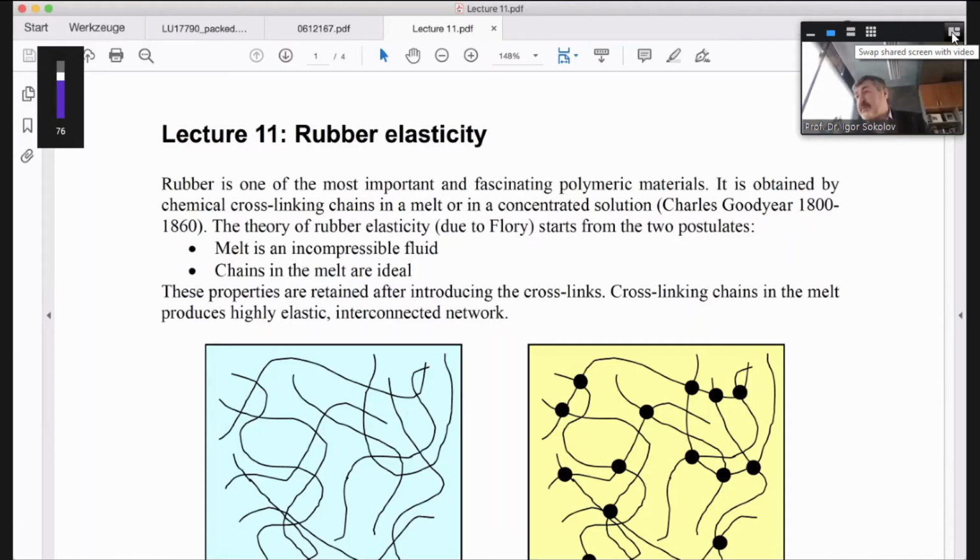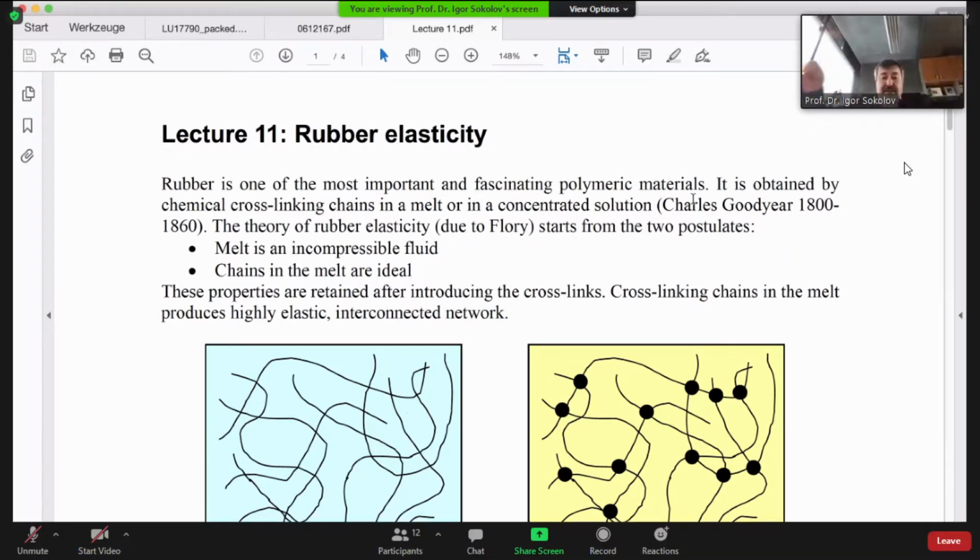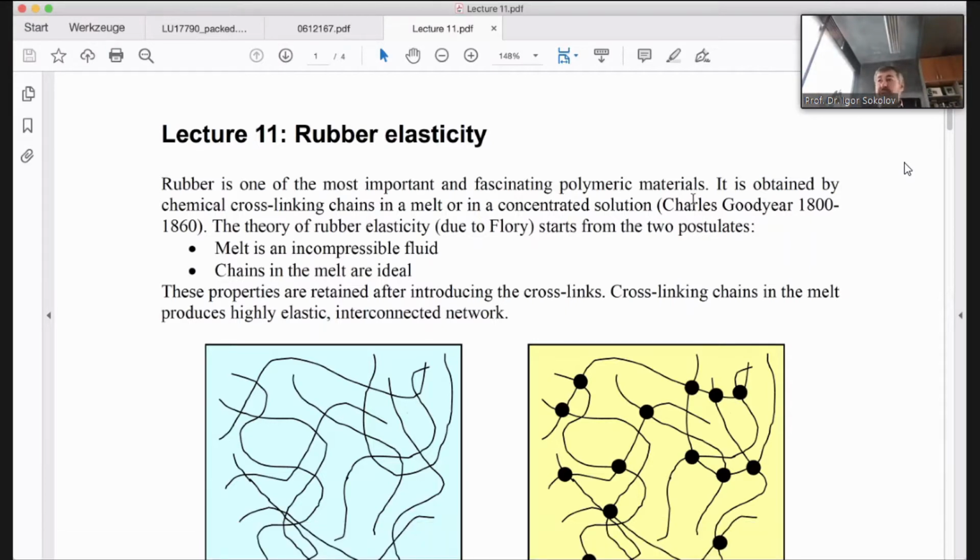This happens because the molecules orient at this place, start to be parallel to each other, which allows for stress relaxation in this system. And essentially the thing flows. And then it tears, it breaks at this place because nothing can prevent this flow.